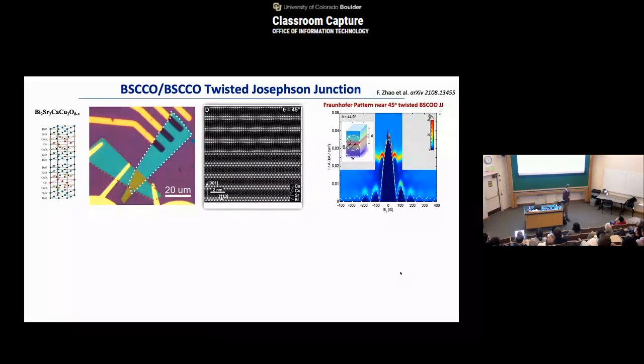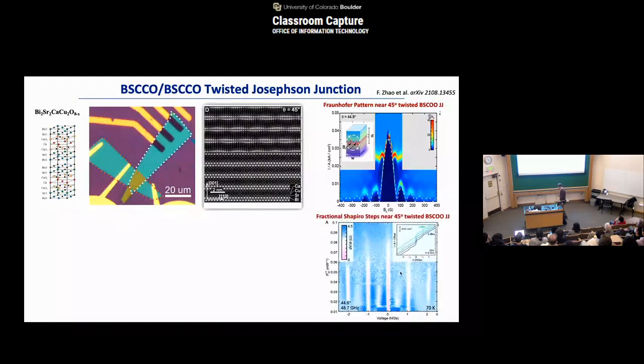For example, you start to see this nice Fraunhofer pattern appear in this type of Josephson junction, whose periodicity cannot be explained by just looking at the structures alone. Moreover, when you shine microwaves, you start to develop so-called fractional Shapiro steps, which can only be explained in terms of a special degree of freedom appearing at this interface.